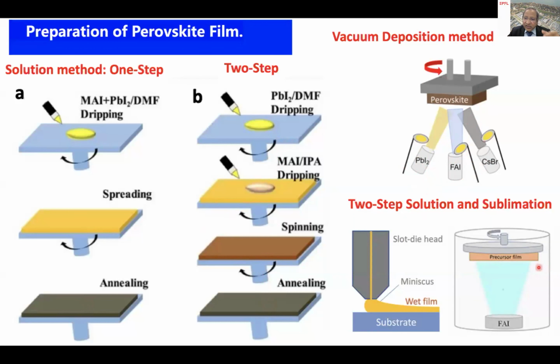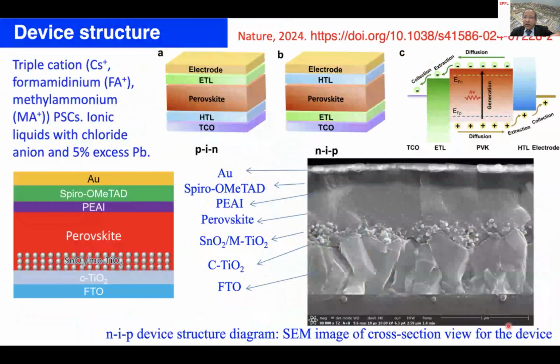The fourth one is industrial application, where you first deposit lead iodide in a wet process, and it is exposed to the vacuum chamber where you have an organic halide cation, and it forms a perovskite. So these are the deposition techniques, but there are 2 configurations known in the literature. One is called PIN, and the second one is NIP.